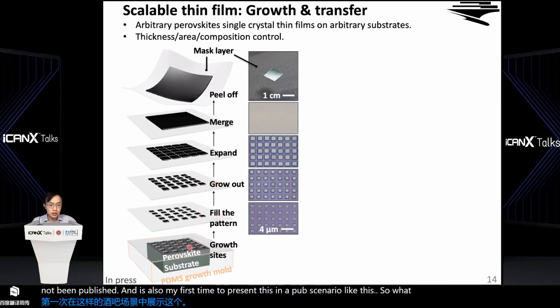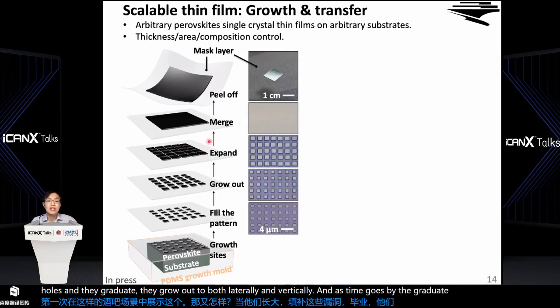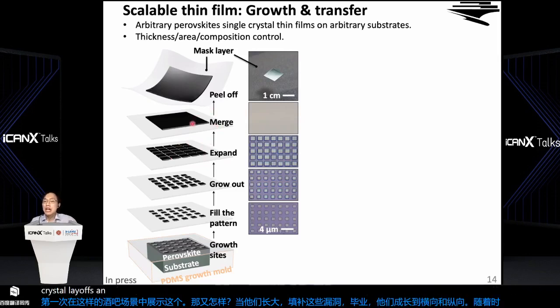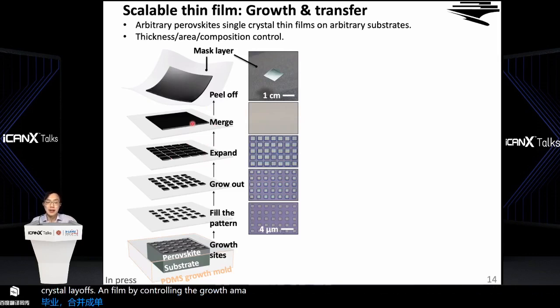this thin film. So we have those patterned bulk single crystal, and we have those masks on top of it. These masks have those defined holes where you want to grow those single crystal perovskites. When they grow and fill those holes, they gradually grow out both laterally and vertically. And as time goes by, they gradually merge into a single crystal layer of thin film. By controlling the growth parameters such as the precursor solution concentration, growth temperature, and so on and so forth, you can control the thickness of this thin film.